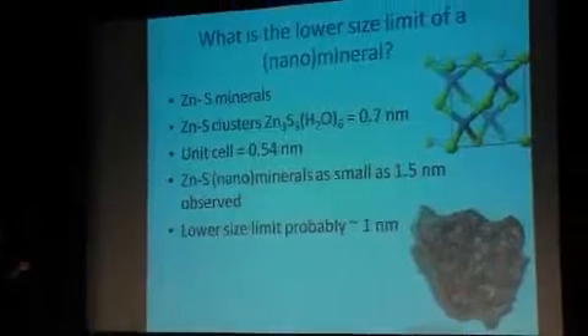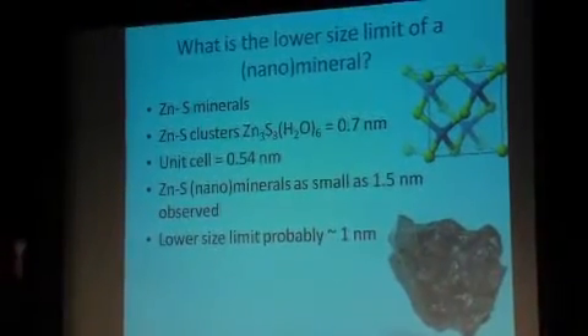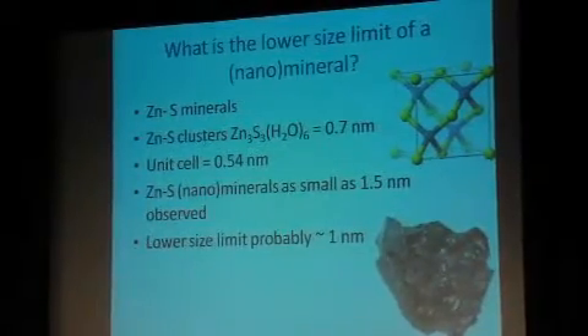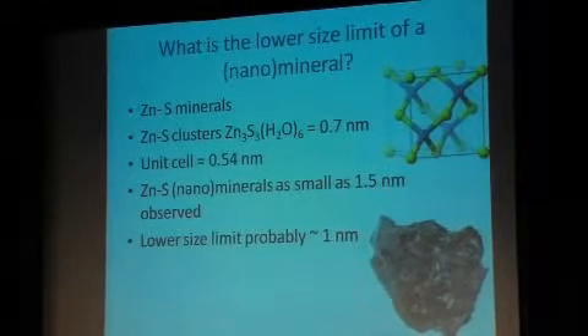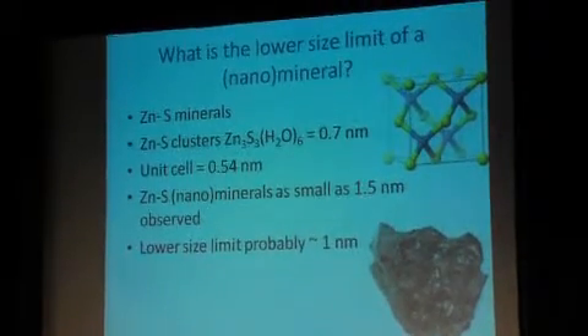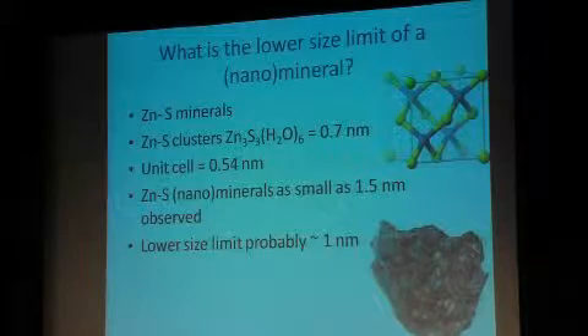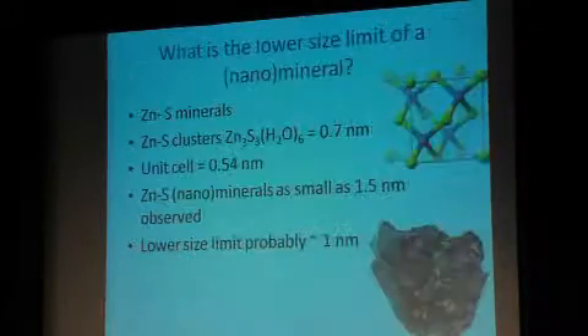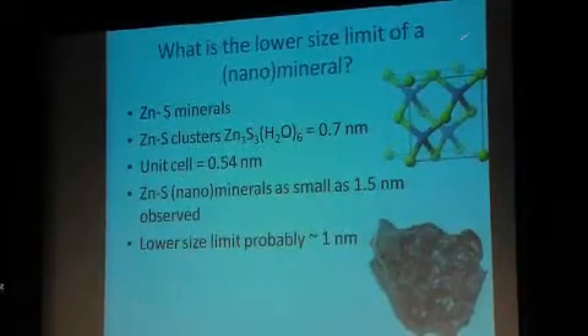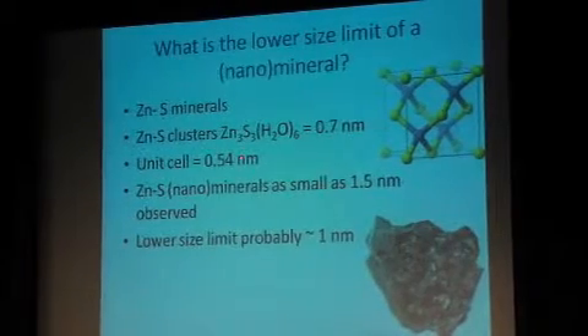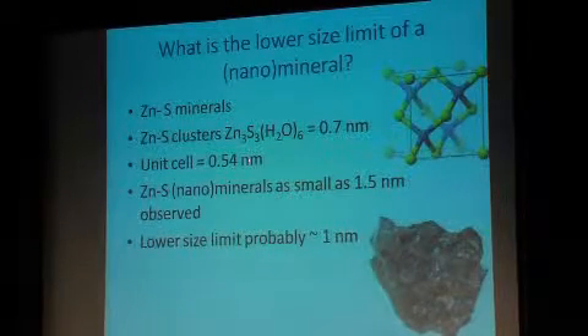One thing that the geologists have really been focusing a lot on, which we haven't discussed as much here, just a little bit, is what's the lower size limit of a nanomineral. So there are zinc sulfide minerals, such as sphalerite, for example. We know that in water, you can have zinc sulfide clusters that have been measured to be about 0.7 nanometers in size. The unit cell size for these minerals is about 0.54 nanometers.